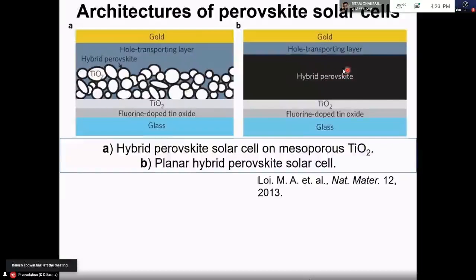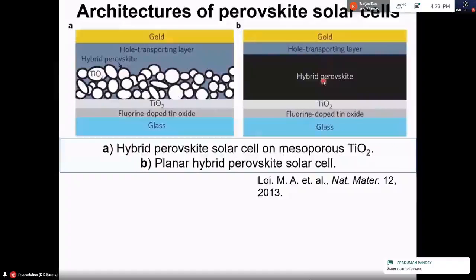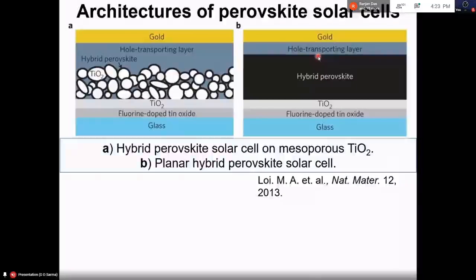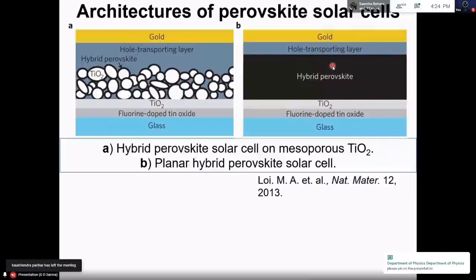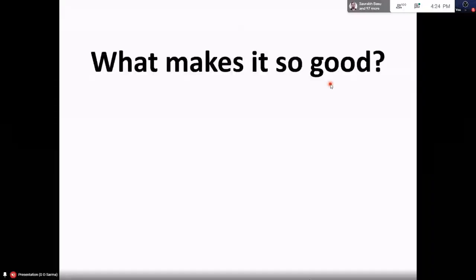This is not only a very good absorber that creates electron and hole, but it also is a very good transporter of both electron and hole, such that the electron goes this way, the hole goes that way, and then you put an electron blocking layer there, which is the hole transporting layer, and you put a hole blocking layer, which becomes the electron transporting layer, and you can tap out the electron and hole from this system quite easily. That means this has very good absorbing property and very good transporting property. So now let us ask the question: what are the fundamental aspects of this material that make it so good, that it gives such fantastic efficiency so easily?